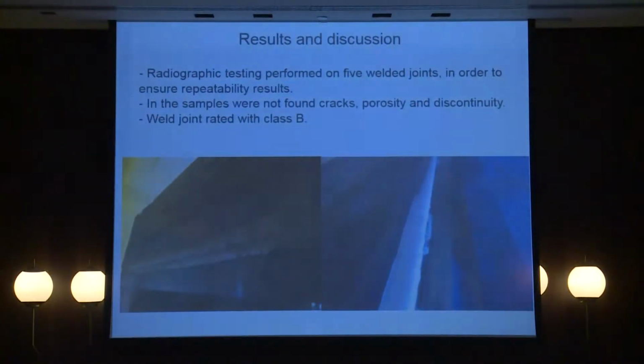Results. Radiographic testing was performed on 5 welded joints in order to ensure repeatability of results. In the samples, no cracks, porosity, or other discontinuities were found, and the weld joint was rated with class B.